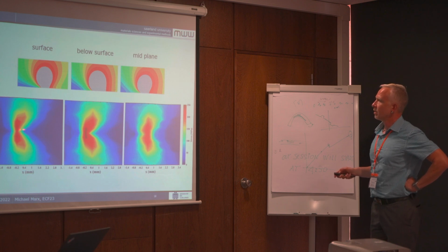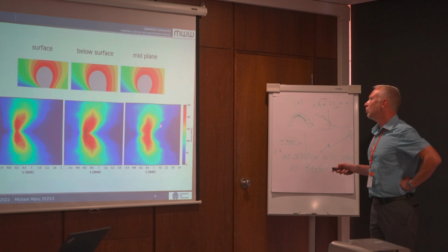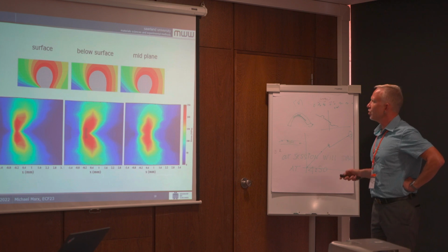So here again, it's on the surface. Here below the surface, we have an increased area of high stresses, and not really in the middle. This here was the calculation for the middle. This here was the lowest depth we could measure.